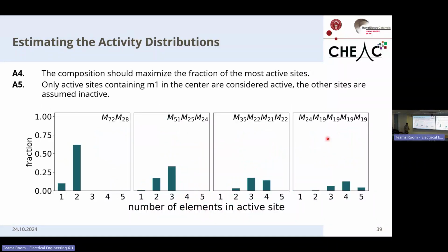So now, having all these definitions, we can start to calculate our activity distributions. And here I decided to go with 2 additional assumptions. One is we are interested in compositions that will maximize these most active sites. So the compositions you can see over here will maximize the fraction of the most active and most complex site that there is. And also, to simplify everything else, we assume that only active sites containing metal 1 in the center are active, and the rest can be ignored and considered inactive. So we see the following thing happening.